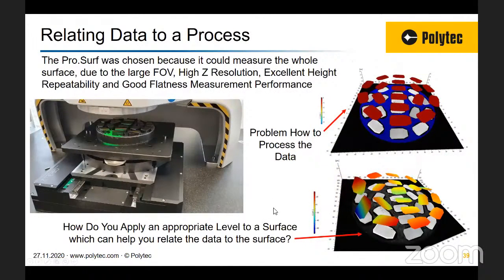So here we use the ProSurf for measuring this. The polishing block here is 150 millimeters in diameter. The thickness of the optics is about 5 millimeters. You can see how we measured the whole surface with the ProSurf, and that measurement took less than 3 minutes. You can separate the bottom surface data set from the top surface data set, and you can see then individually each of the ground optics.